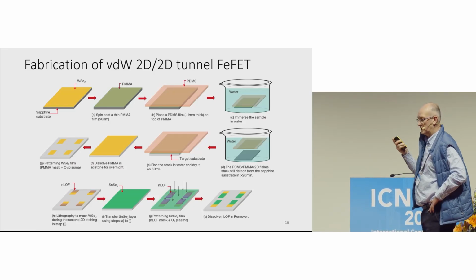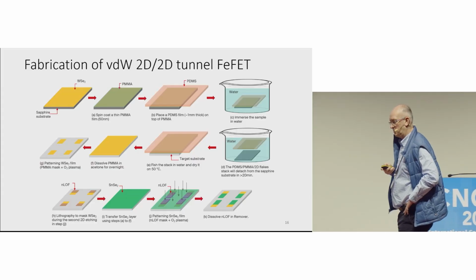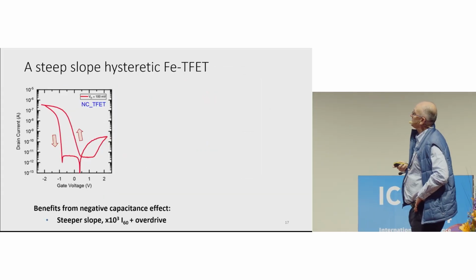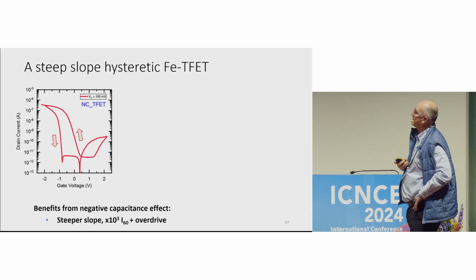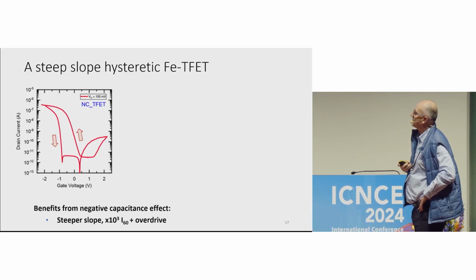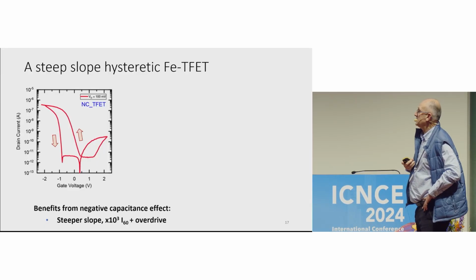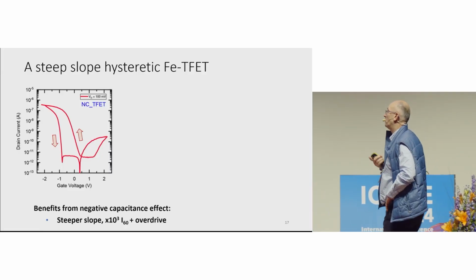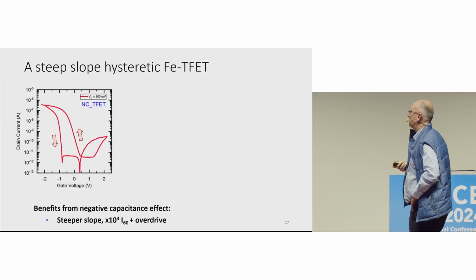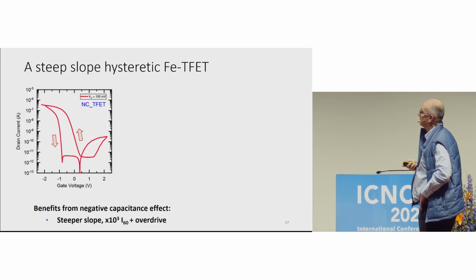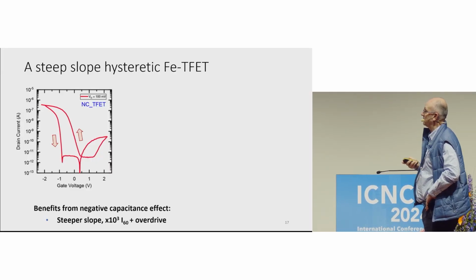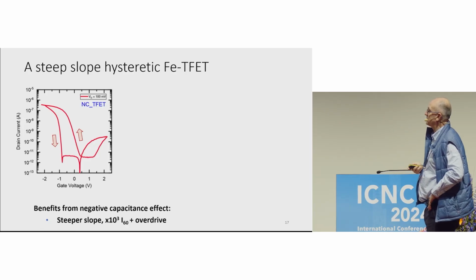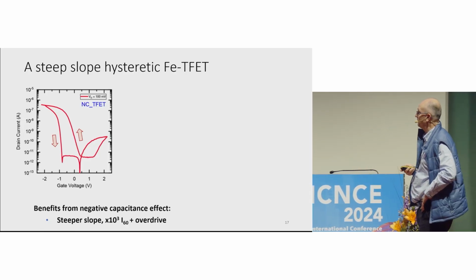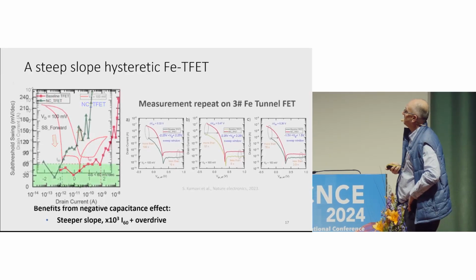This is in the PhD thesis of Sadegh Kamae at EPFL, it's a public thesis. So this is the type of memristive device that we achieve, we call it negative capacitance tunnel FET. It is not fully matched to a clean hysteresis, and we obtain practically a steeper slope. I think this is the smallest slope obtained in such a device, and we multiply by a factor of 1,000 what is called the I_60 current, which is the region of current where the slope is smaller than the sub-thermionic limit of 60 millivolt per decade. And we have an overdrive that is significant.